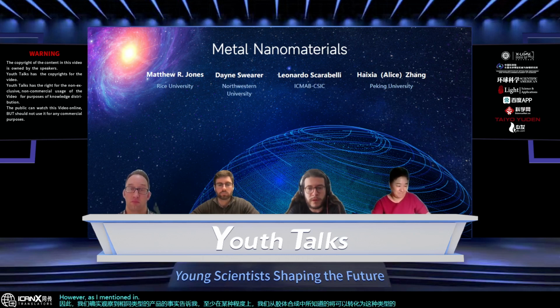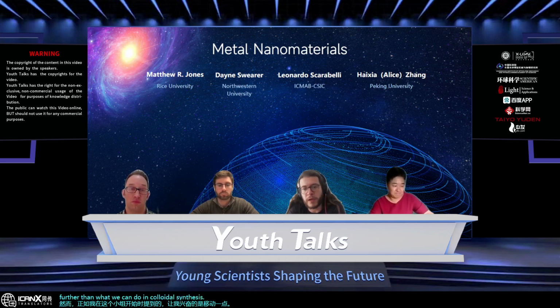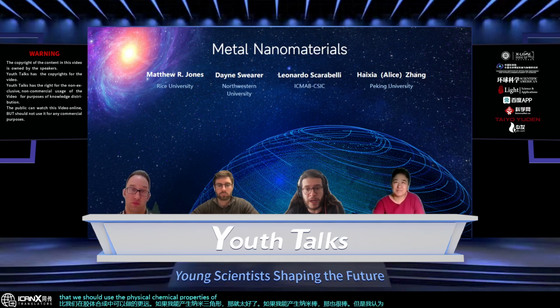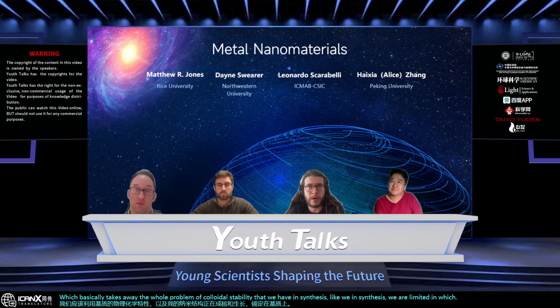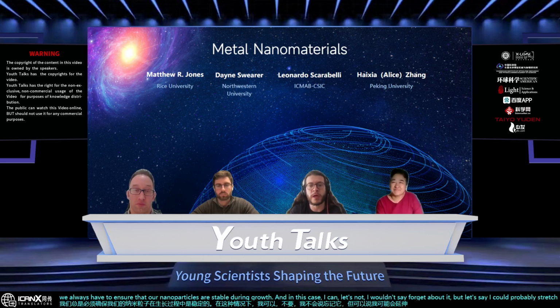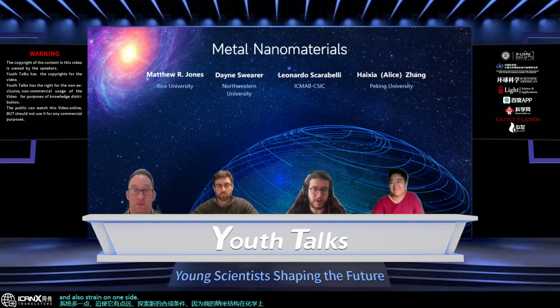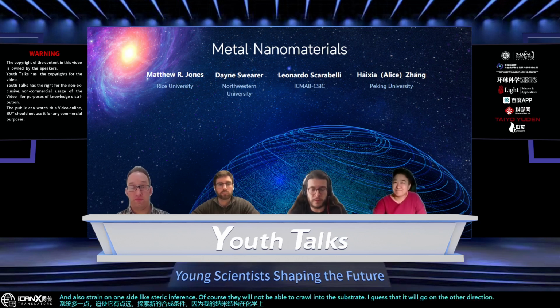However, as I mentioned in the beginning of this panel, what gets me excited is to move a little bit further than what we can do in colloidal synthesis. It's like, okay, if I can produce nanotriangles, that's great. If I could produce nanorods, that's also great. But what I think is that we should use the physical-chemical properties of the substrate and the fact that my nanostructures are nucleating and growing anchored to the substrate, which basically takes away the whole problem of colloidal stability that we have in synthesis. In synthesis, we are limited in which type of chemical environment we can use, because we always have to ensure that our nanoparticles are stable during growth. In this case, I wouldn't say forget about it, but I could probably stretch the system a little bit more, force it a little bit further away and explore new synthetic conditions because my nanostructures are chemically bound. And also there is strain, like steric hindrance; of course, they will not be able to grow into the substrate. I guess they will grow in the other direction. So those are the things that I think are more promising for this type of system.